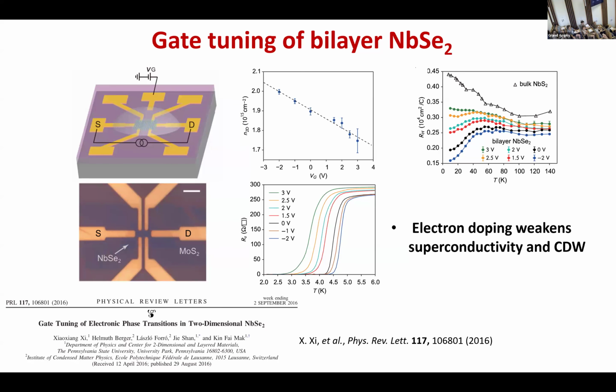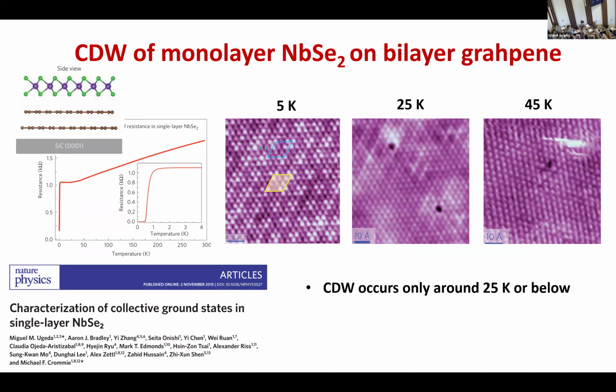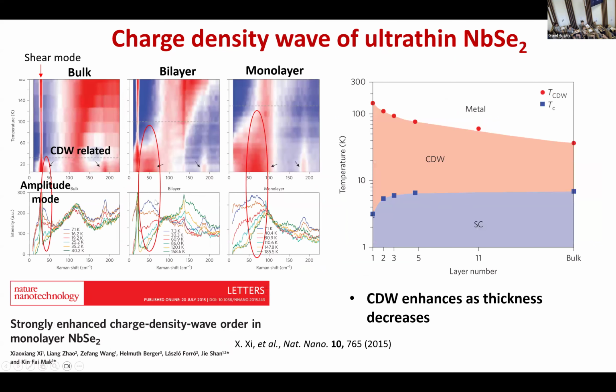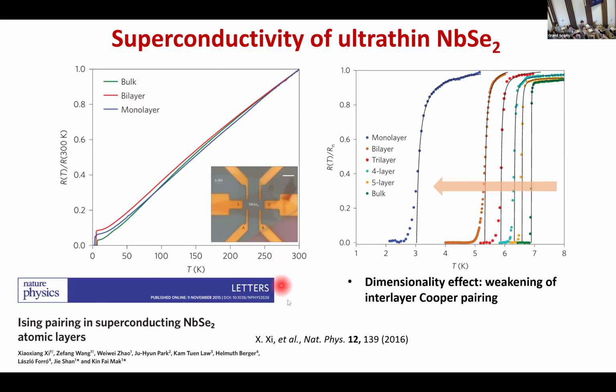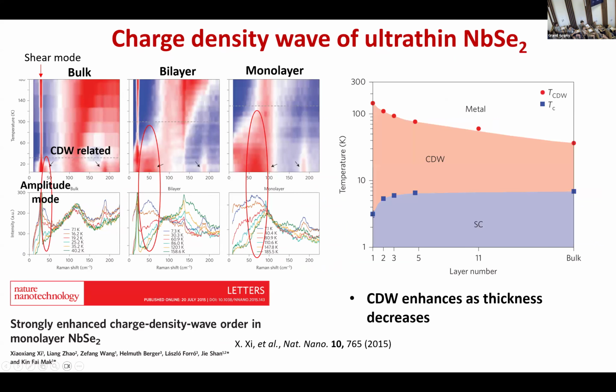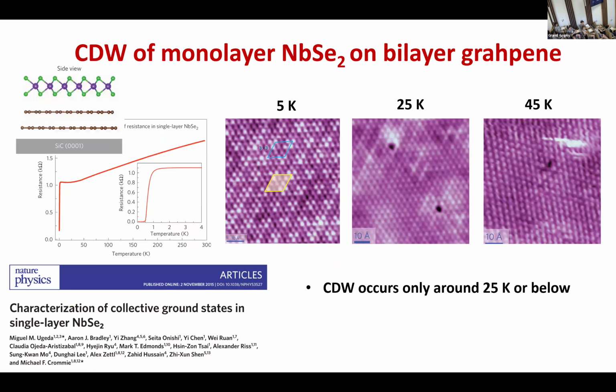So I think this is consistent with this picture, that when you grow niobium diselenide on graphene, graphene can transfer a lot of charges, electrons, to your niobium diselenide. So that's why the TC they observe here is lower than exfoliated. The exfoliated one here is 3K for monolayer, but when you grow this, you get only 0.5K. And because of this doping effect, the charge density wave also gets weaker.